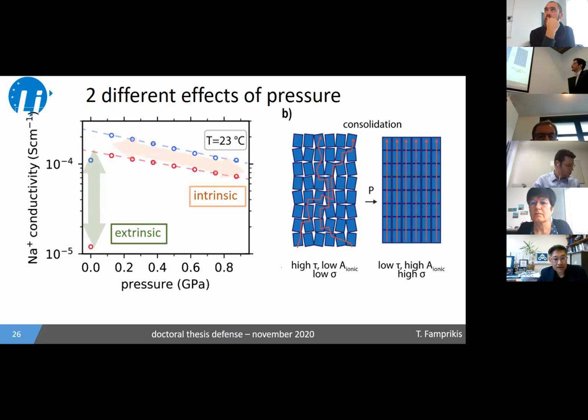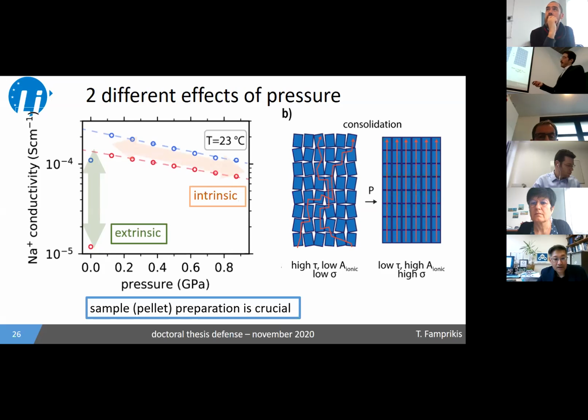talked about before. So what comes out of this is that most of the studies report conductivities at zero applied pressure, and we need to be very careful about how we make the sample, in this case a pellet, and how we report the results. And also, perhaps measuring under pressure and extrapolating the value at zero pressure might be a more reliable and reproducible way to compare the work between labs.